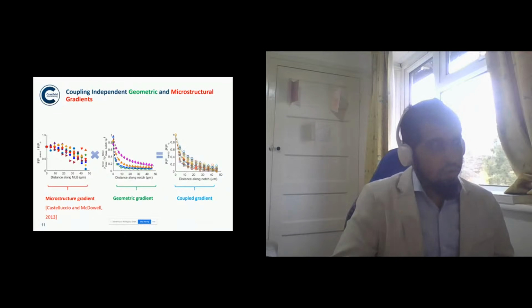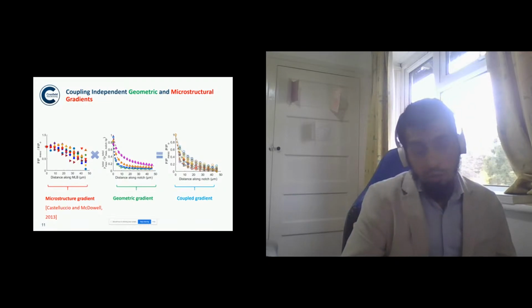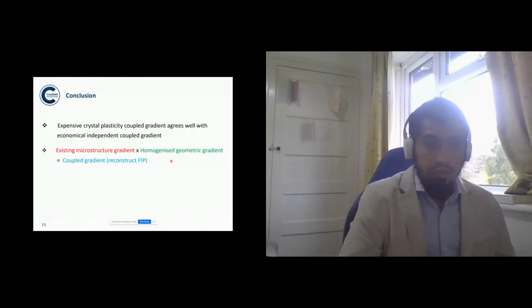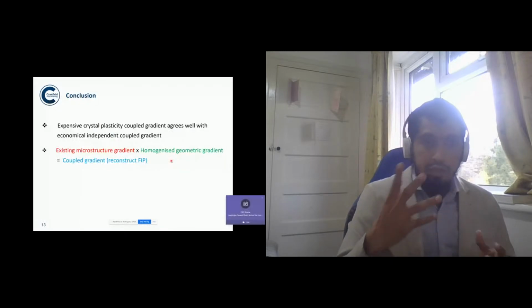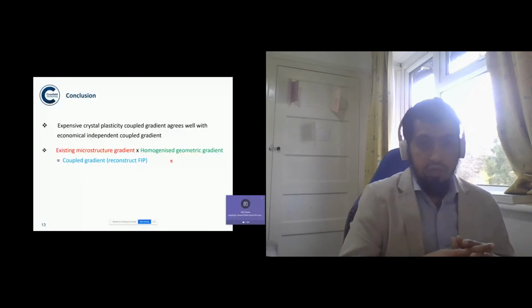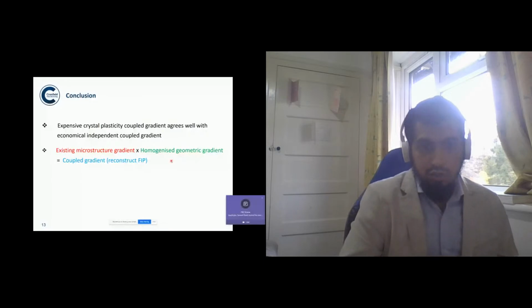So following on, we conclude that the expensive model agrees well with the economical model, and that gives us the advantage of calculating the independent geometric gradient coupled with the microstructure gradient to, for example, come up with the coupled effect of both the gradients. And as we broaden the scope of this approach, this gives us the advantage that,